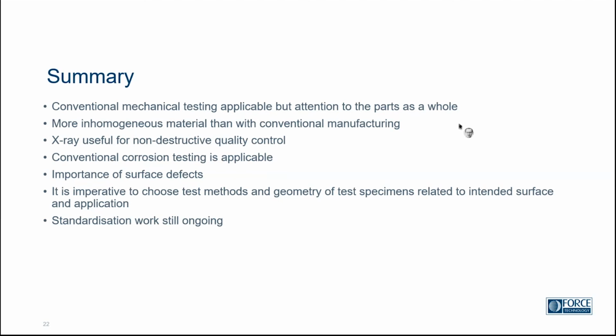We saw from MX3D that we have parts used in traditionally, and still, very corrosive environments. So it is indeed possible. From my perspective, I of course have to have a very critical eye to it, but it is indeed possible, and we see WAAM manufactured parts applied in aerospace, which is an area where you have extremely high standards for quality control and assurance.